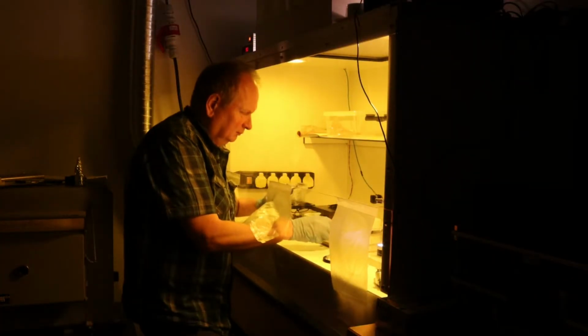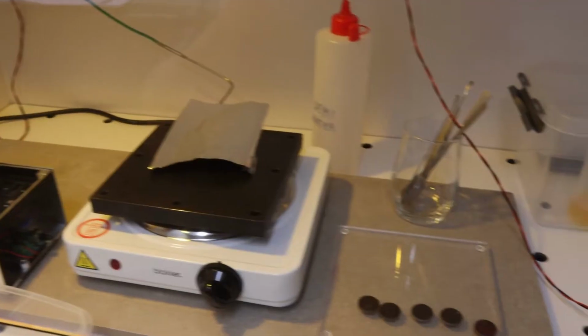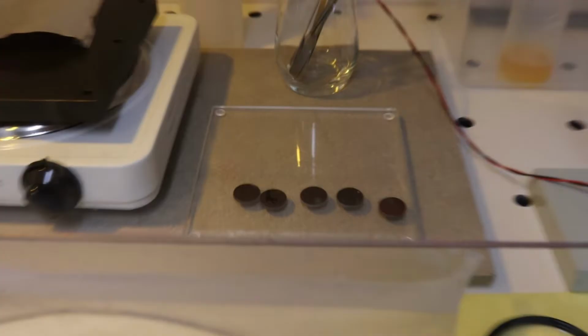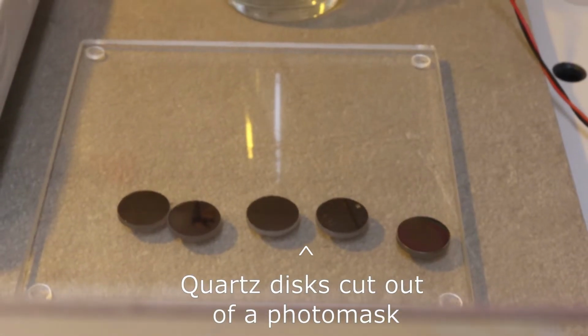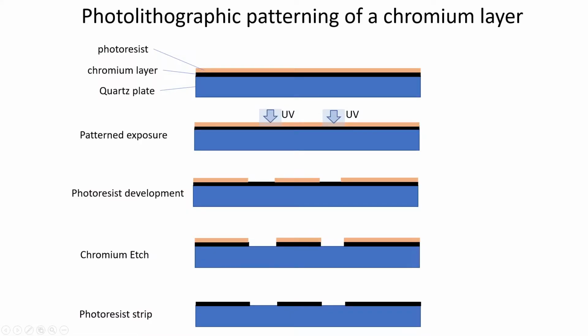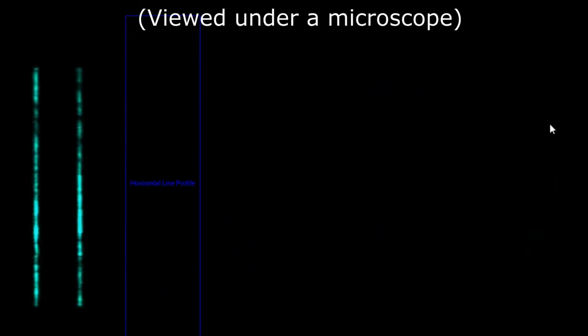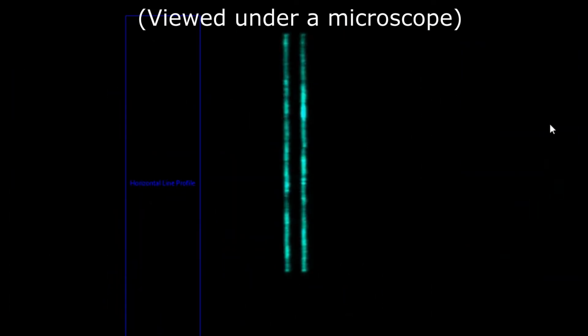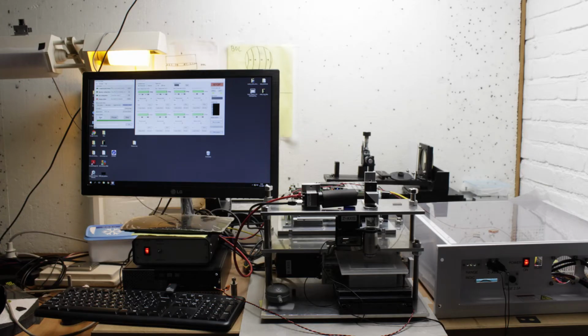The way I made these slits is by etching the patterns into a thin chromium layer, and I used old lithographic photomasks for this purpose. Now, to etch the patterns I used a photoresist layer and exposed this layer with UV light in the pattern of the slits. After that, the photoresist was developed and the chromium underneath was etched in the desired pattern. Now, the result is tiny transparent slits in the chromium layer. By the way, the exposure patterns in photoresist were produced by using the do-it-yourself maskless wafer stepper that featured in several of my previous videos.